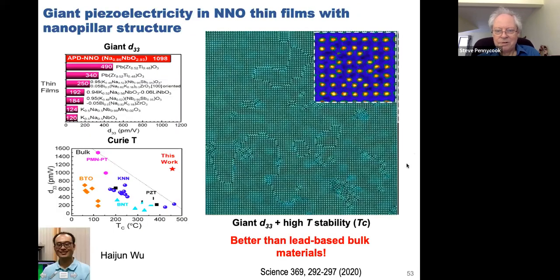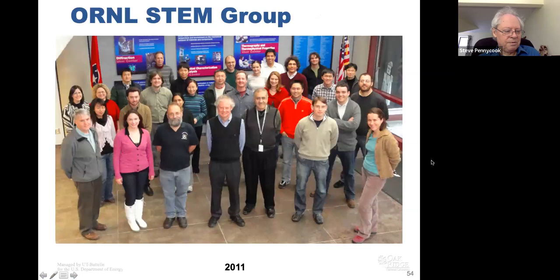And my last student, actually this was my first student, just to show we still do materials studies. In fact, most of the work was on materials, but this is trying to get lead-free piezoelectrics. And this is his crowning achievement here, using thin films of sodium niobate. You get all these translation domain boundaries. And these are incredibly responsive, and you get the largest piezoelectric response so far found. Much larger, in fact, than the lead-based material. And it's also more stable. So this is also a great breakthrough. We patented it, but that was just a rather rushed run through.